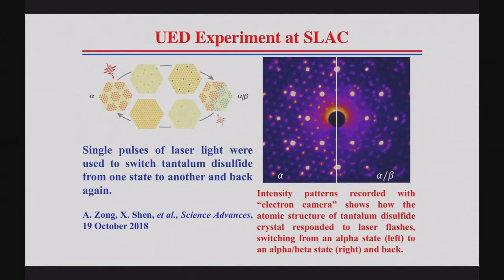And then, interestingly, if you send another pulse through the material, this material transforms back to the alpha structure. So as you can see, this can be used as a switch. Just with one electron pulse, you can change the structure of the system and go from one phase to another. And with one pulse, this domain wall completely dissolves, and you recover the pristine alpha structure. And so this could be very good for data storage.